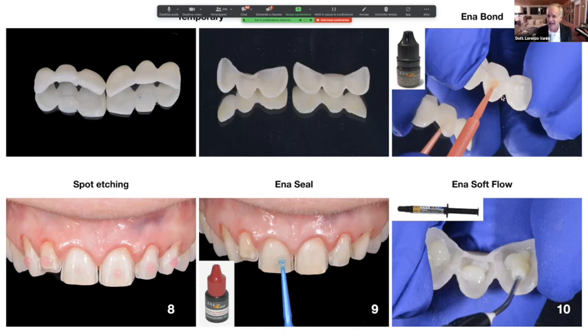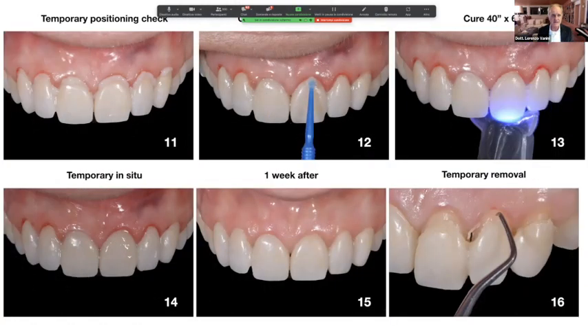This is why I use Enabond, because I want to have a strong bond between the resin of the temporary and the Enaflow. Spot etching. Ena Seal is different from Enabond. It doesn't contain primer, and it doesn't work like an adhesive system. This is a complete adhesive system. This is only fluid resin. Then I put Enaflow inside, and you have to remove the excess, especially in the interproximal areas, and then you have to cure.